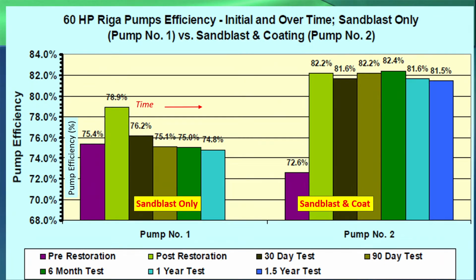I think this is a pretty eye-opening slide, too. This one will really show a lot because this is going to be over time. So this is on the 60 horsepower pump, the initial and over time, the sandblast only versus sandblast and coat. You can see here the sandblast only on this pump on the 60 horse. Before it was done, you're at 75.4%. Post-restoration, you're getting up to 78.9. Not really that great, but you're running a little bit better in the pumps in service.